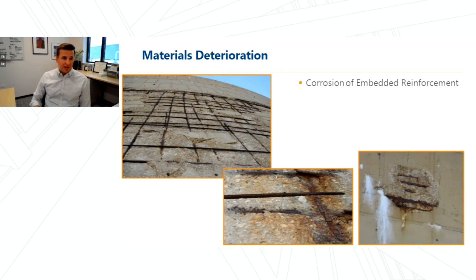Most concrete has a naturally high pH on the order of 12 to 14. And that high alkaline environment protects the embedded reinforcement through a passivating oxide layer. And there's two main sources of disruption to this passivating layer that when disrupted, corrosion can initiate. The first is a reduction in pH. This is most common due to carbonation, i.e. a reaction with carbon dioxide. And this can occur naturally just due to carbon dioxide in the air, but it can also occur from concentrated sources that might be present in a power generating or other process environment.